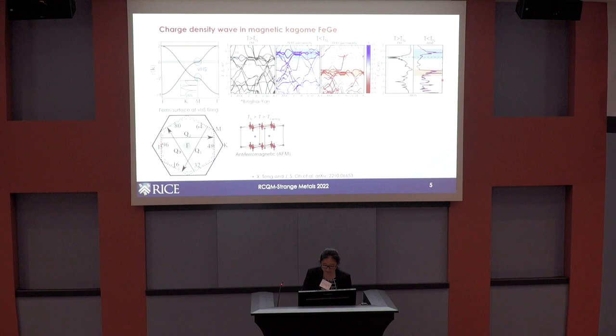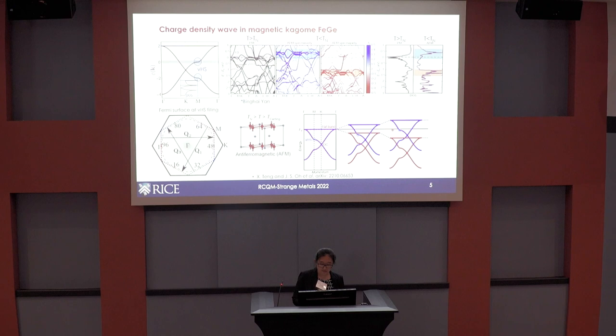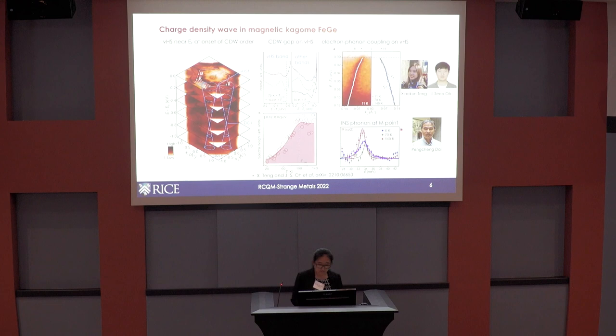The effect can be represented with a simple schematic. Starting in the paramagnetic state, you have spin-degenerate band dispersions. When A-type AFM orders within each layer, exchange splitting occurs such that the spin minority bands shift up in energy. This brings the Van Hove singularities — previously far from the Fermi level — closer to the Fermi level. This is consistent with our observation that at the onset of the CDW order, we observe the Van Hove singularities very close to the Fermi level.